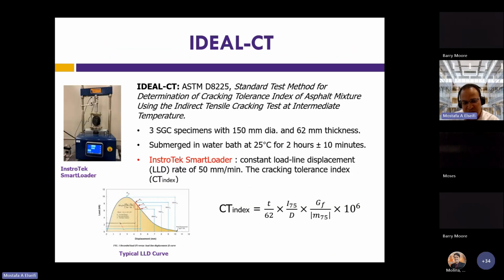For the IDEAL-CT, it consists of loading the specimen on the apparatus shown here, and you create this plot of load versus displacement, and then you calculate something called the CT index. And again, the CT index is an indication of how much energy you will apply to get the specimen to failure. And again, this is a relatively new test that has been introduced in Texas. And for the CT index, there is no real national value or threshold to assess it until now. But VDOT uses 100 for the CT index. Other states use a slightly lower value, but again, this is the value that we use in our evaluation.